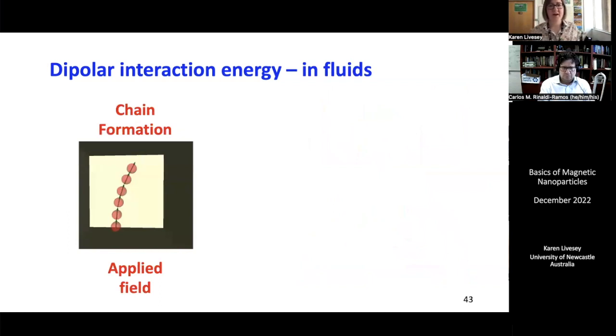If we have particles in fluids, we know they can move around to try to minimize dipole-dipole interactions. So in an applied field, we often get chains, and this is from a simulation we made many years ago. You can see the magnetic nanoparticles form some chain, and if you can see the little green arrows here, that's the macrospin moment in each one. So they're trying to line up tip to tail because that gives us the lowest dipole-dipole interaction.